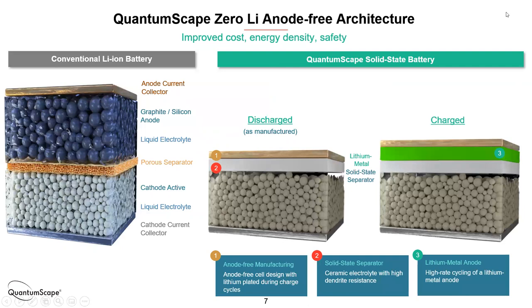This is what it looks like if you can make that lithium metal anode work. So I copied the lithium ion structure again on the left, and then basically to scale, the solid state lithium metal system that Quantumscape is working on looks like these pictures here on the right. And so I'll start you with the center picture. This is what it looks like when we fabricate the cell in the factory. So we start with a cathode material that's actually very similar to conventional. So it can be based on NMC, nickel, manganese, cobalt. It can be based on lithium iron phosphate or some other chemistry.